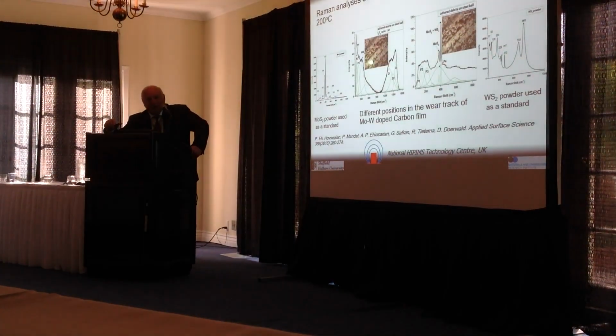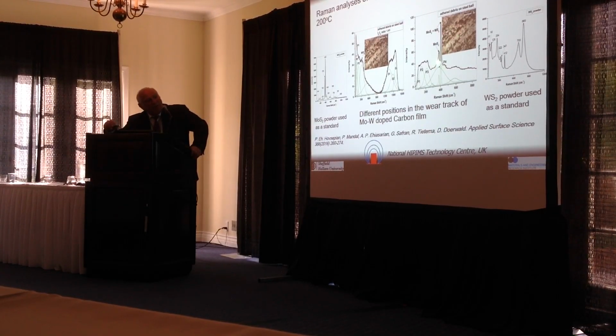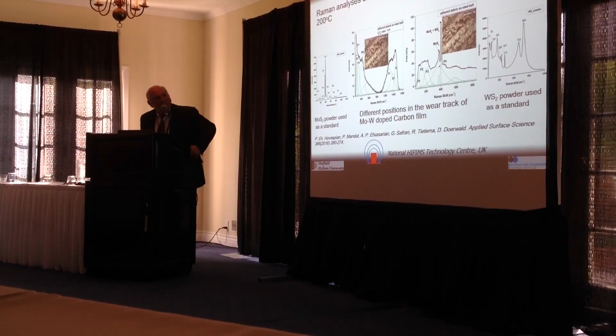The formation of the MoS2 and WS2 in situ was confirmed by careful analysis of the wear debris after lubricated test at 200 degrees C. And you can see the spectra here of the wear debris. And here, these are the spectra of these two compounds in pure powder condition. We can clearly see that these lines correspond exactly to the powders which we use as control